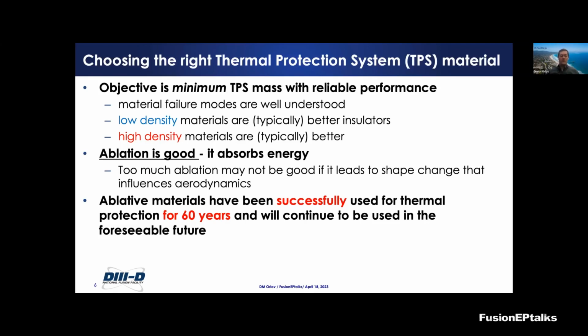The minimum objective for the thermal protection system, with a reliable performance, is that the material failure modes need to be well understood. And when we choose the thermal protection system materials, usually we choose between the low density materials, which are typically better insulators, or the high density materials, which I'd say are typically better ablators. Because ablation is a good process. Ablation usually absorbs the energy, but too much ablation may not be good because it may lead to shape changes, as you will see in some future slides. And these shape changes can change the aerodynamic behavior of the spacecraft that are in the atmospheres.